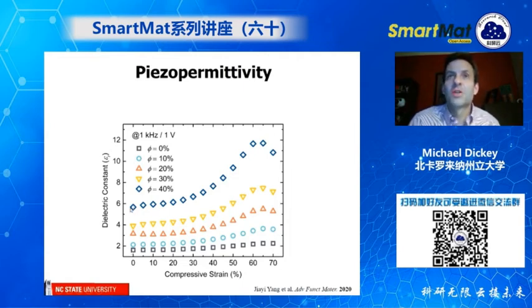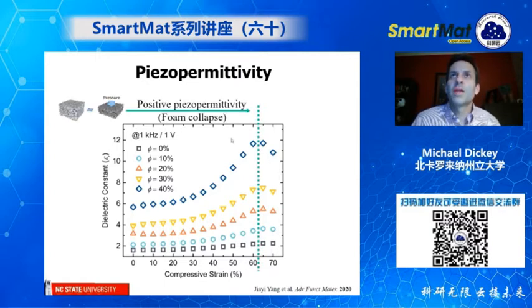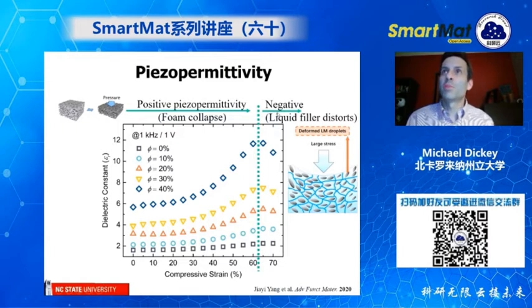Now you'll notice something very interesting. First of all, the dielectric constant goes up, and then very strangely, it goes down. So let me talk about this. Here's a line that divides the part that goes up and the part that goes down. The part that goes up is easy to understand because remember, we have a foam, and when we push the foam, we're just pushing the air out. So we're taking something that has a lot of air here, and here it has less air. Now, once all that air is pushed out, we actually get a decrease in dielectric constant. So we call this a negative piezo permittivity.